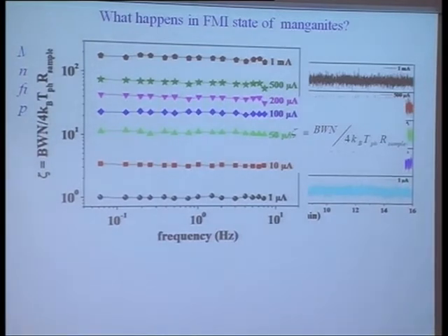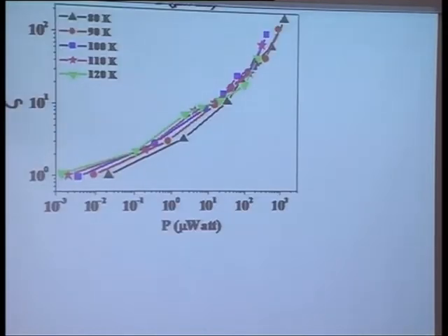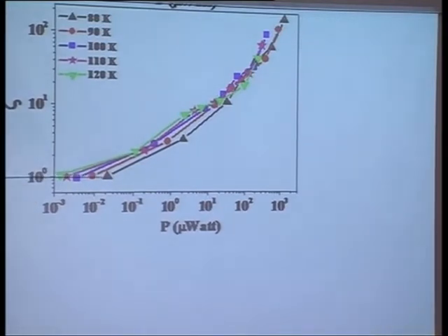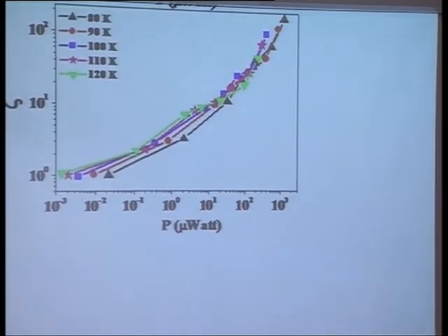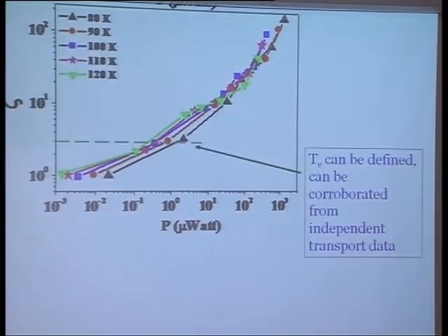Now just to pack the talk here, I just show you one little view graph. If I measure this quantity, which is the ratio of the background noise divided by 4 kBTR, which a good man like Nyquist had given us, and we measure it as a function of power, then obviously it is 1 when the power is low. So, you know, you have no problem in the world, everything is in equilibrium, there's no conflict in the world. But what happens is that up to a power of about a microwatt, we see that the electron temperature becomes about a couple of times more than the phonon temperature. And if we measure the resistance and use the resistance as a thermometer of the sample, we can find out the electron temperature. If we do that, we find that beyond this power, we enter into a regime where the electron temperature has decoupled from the phonon temperature.